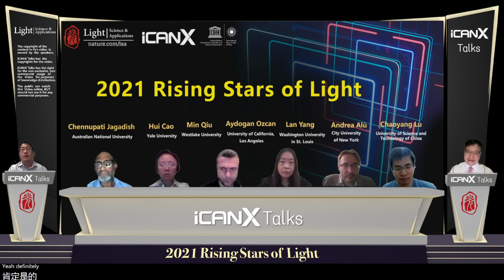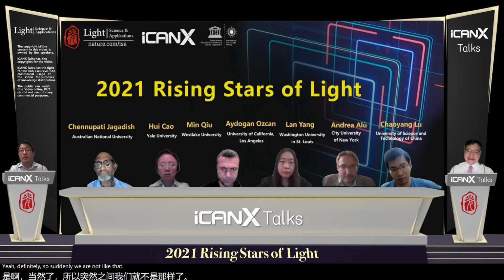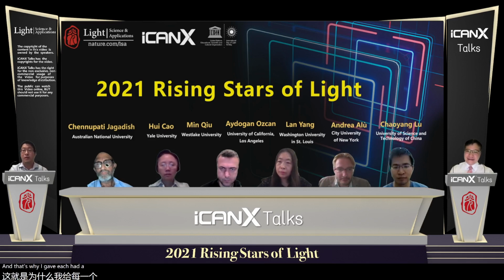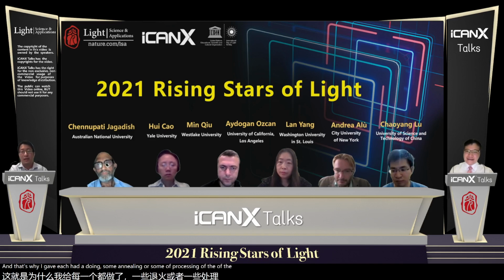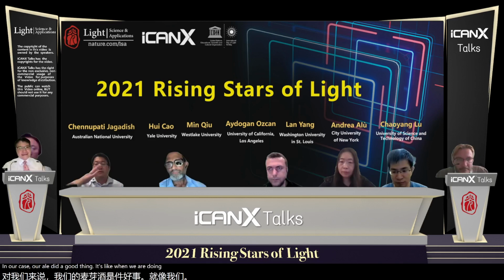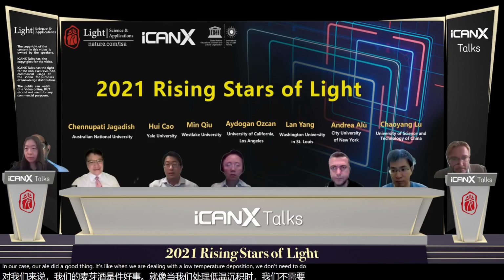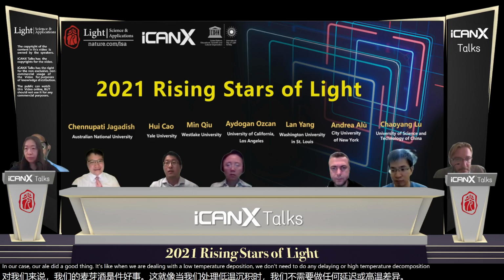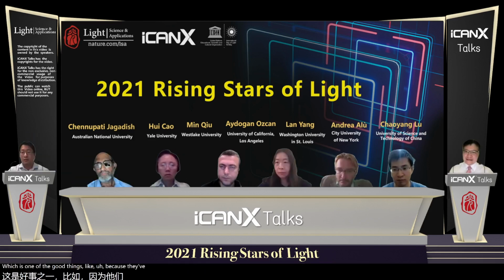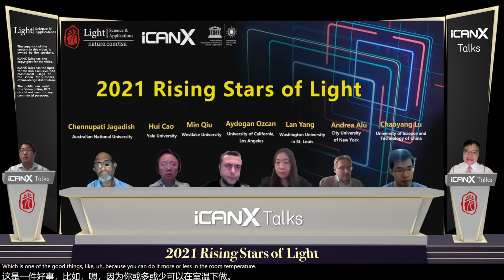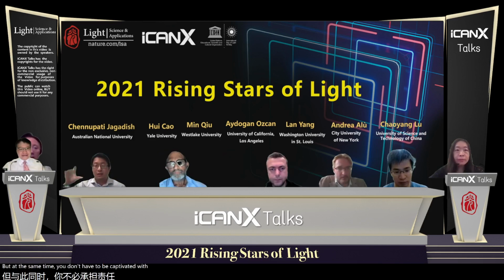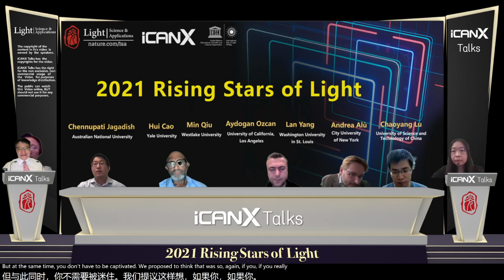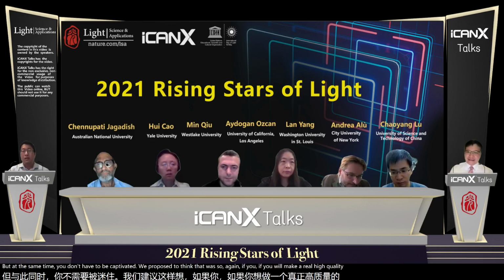Yeah, definitely. Certainly we are not a single crystal material, and that will enhance certain losses. That's why if you do some annealing or post-processing of the material, you can reduce the losses. In our case, with ALD, the good thing is that we're doing low temperature deposition. We don't need to do any annealing or high temperature deposition, so you can do it more or less at room temperature. But at the same time, you don't have the capability to post-process those. So if you really do a high quality fabrication, definitely you can reduce the losses.